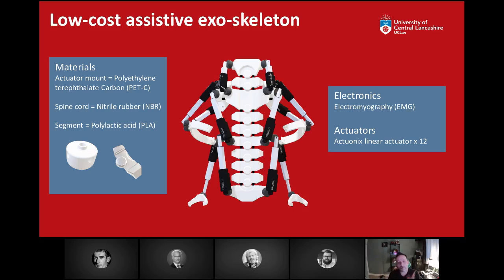So we knew that this was not going to be a low-cost assistive methodology. We then thought, you know what, let's just print it. Let's just take some standard polylactic acid, some PLA off the shelf, and started printing, and we printed it. Interestingly, we found some fascinating results. We found that the polylactic acid was actually active. It could support the body better than we ever imagined. It had so much potential behind it. Now, this system itself uses linear actuators.